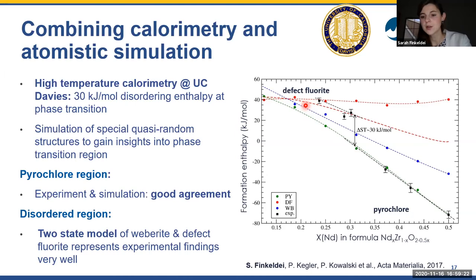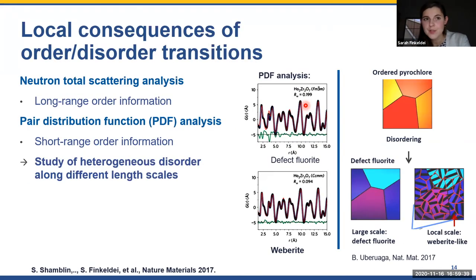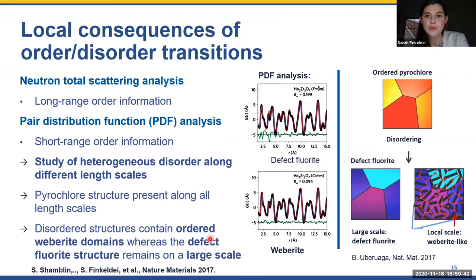Because the first indication we got for it was actually in time-resolved laser fluorescence spectroscopy measurements, where we saw some remaining order in defect fluorite structures. And the first proof we got was with a PDF analysis of our neutron total scattering data, where we found that when we look at the diffuse scattering with the PDF, at the local range we can only describe our data with a weberite structure.